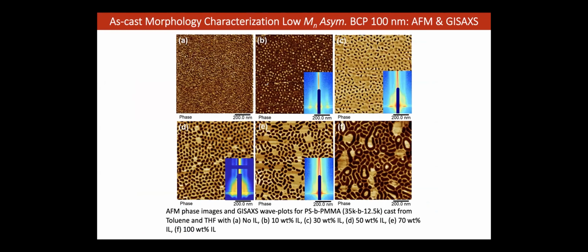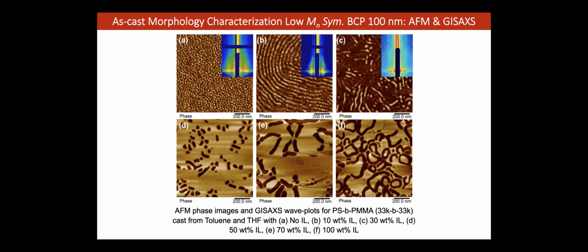Here are some illustrations of GISAXS on, again, asymmetric block copolymer systems. In this case, it did not really give us a very good vertical orientation for almost any concentration. So this is a 35-12 molecular weight, cast from toluene with ionic liquid. And maybe you can argue that somewhere between 10 and 30% is your best shot for getting the best vertical ordered membrane. But in general, this is not great. And there's also the film thickness issue with 100 nanometer. So a number of problems to be figured out, but we can really learn from GISAXS conditions for that that are critical for this. Very simple, add ionic liquid and you get vertical orientation.